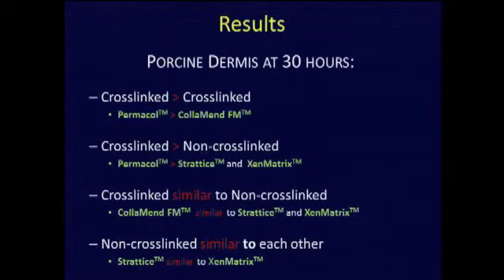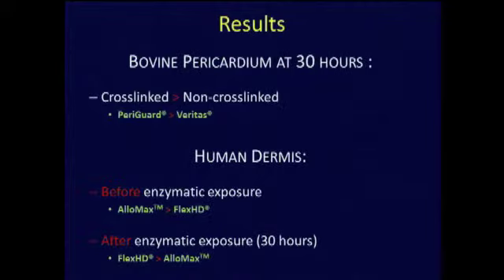In terms of porcine dermis, if you categorize these as cross-linked versus uncross-linked, the cross-linked materials had a greater tensile strength, a greater tensile strain, and a reduced modulus at 30 hours. This likewise was similar for the cross-linked bovine pericardium versus uncross-linked bovine pericardium, thus a potential mechanical advantage of cross-linking in an environment of enzymatic degradation.